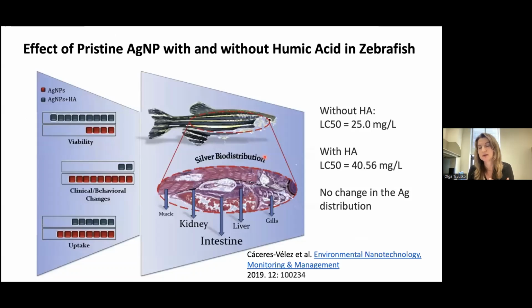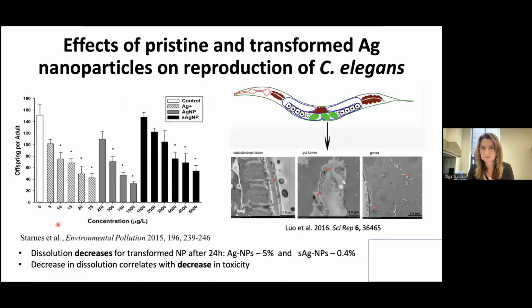Now, I was talking about sulfidized transformed particles. What about humic acid? When silver nanoparticles in the environment get coated with humic acid, what happens? This study in adult zebrafish demonstrates that if you look at the distribution of the particles among different organs, it doesn't change whether they are coated with humic acid or just pristine. However, it does decrease viability if they are pristine, and viability actually increased by 50% when they are coated with humic acid. Also, there is a little less uptake, not by a huge percent, but some.